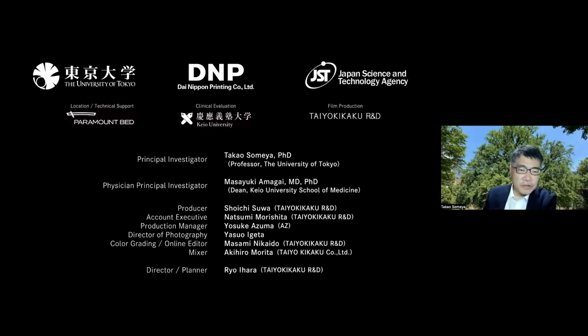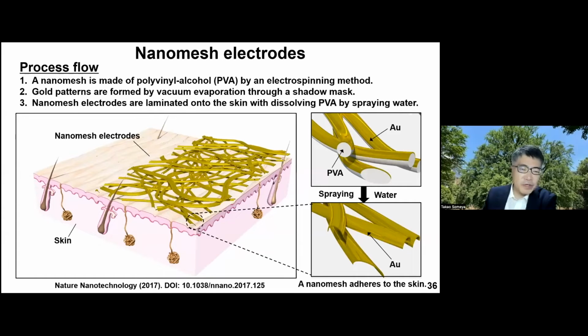So I hope that you like this video, and let me try to explain the details of nanomesh. Nanomesh is made of polyvinyl alcohol by using the electrospinning method, and the gold patterns are formed by vacuum evaporation through a shadow mask. When nanomesh is placed on the surface of skin and water is applied by spraying, the PVA is dissolved in water and washed away completely. Finally, only the gold thin film nanomesh remains on the surface of skin.